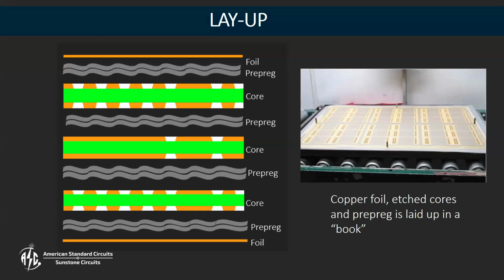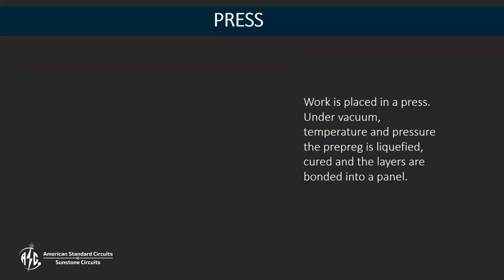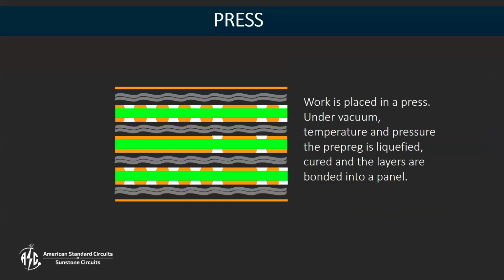And then once you have your book complete, which is generally several panels thick, separated by a Teflon release sheet, we're able to go into the press, where there's heat, pressure, and vacuum applied to the book. It gels the epoxy in the pre-preg layers, liquefies it a little bit. It's able to flow and fill in the gaps. And this is where those low pressure and high pressure areas that we talked about earlier come into play. But this epoxy then flows, fills in all the gaps.